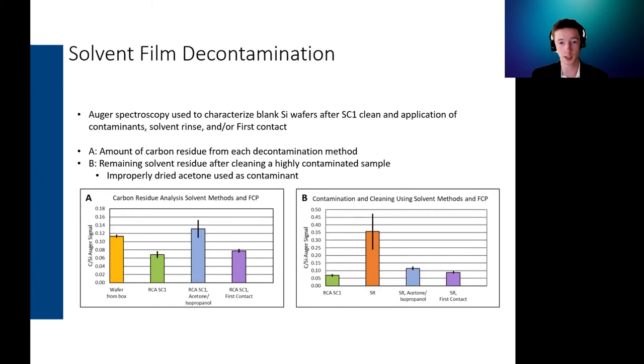The next test that we did using Auger was looking at the decontamination efficacy from solvent film. We did another SC1 clean on a number of samples and then we contaminated it using acetone. We just put some acetone on the sample and allowed it to air dry, allowing the ambient air to contaminate our sample.